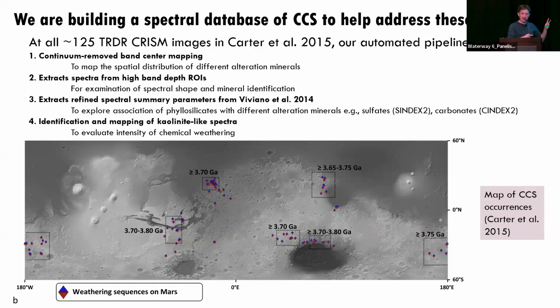We're also extracting spectra from statistically generated high band depth ROIs. We're also extracting refined spectral summary parameters, the ones that come with CRISM and the PDS data, to explore the association between these clays and other kinds of alteration minerals like sulfates or carbonates. And we're also identifying and mapping kaolinite-like spectra to evaluate weathering intensity.